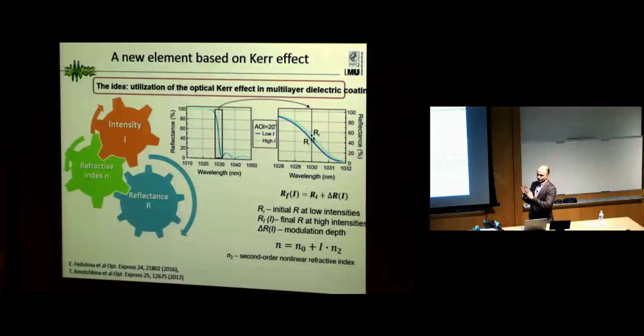Now I was speaking about nonlinear absorption, but I find a much more interesting effect, the Kerr effect, because when you work with absorption it's very difficult: your material starts to absorb energy and then the temperature grows. The Kerr effect is always the more interesting one. And to observe the Kerr effect, we produced a structure like a filter, as shown here. If you zoom into this range, the filter looks like this. The structure is made in a special way so that it provides higher reflectance at low intensity and lower reflectance at high intensity. It means that for different intensities, we can get two different reflection values.